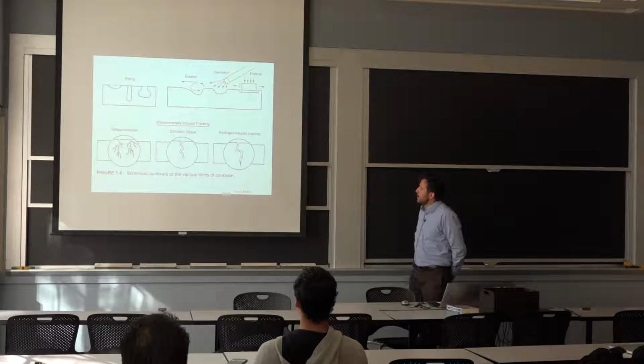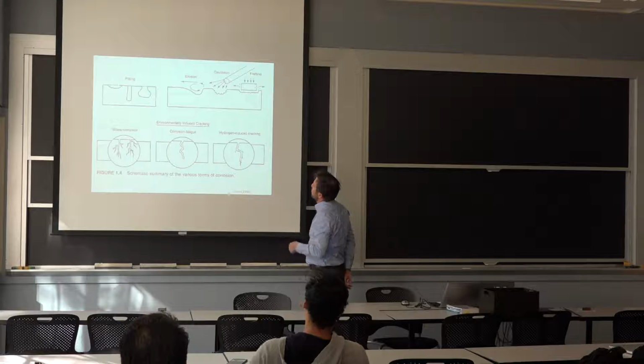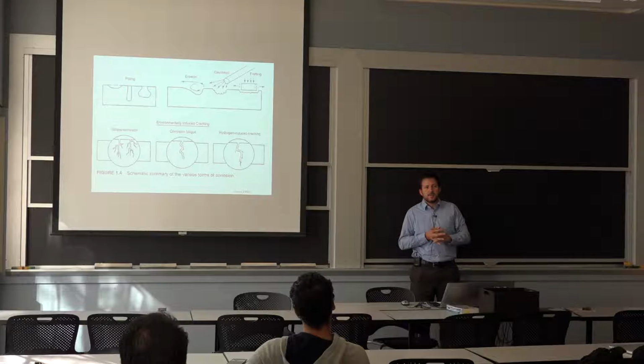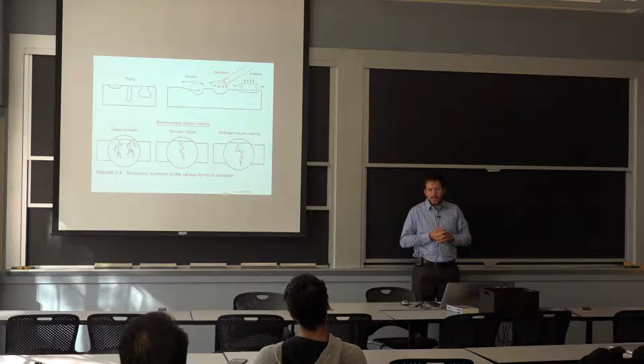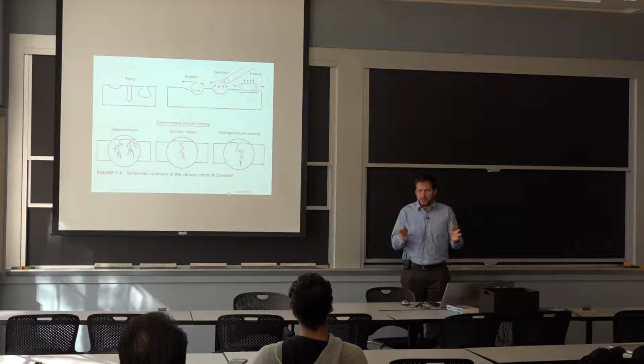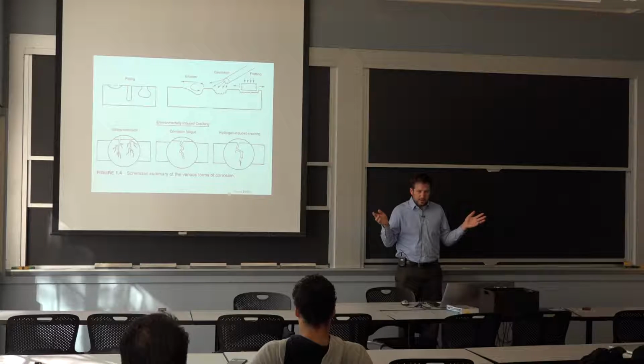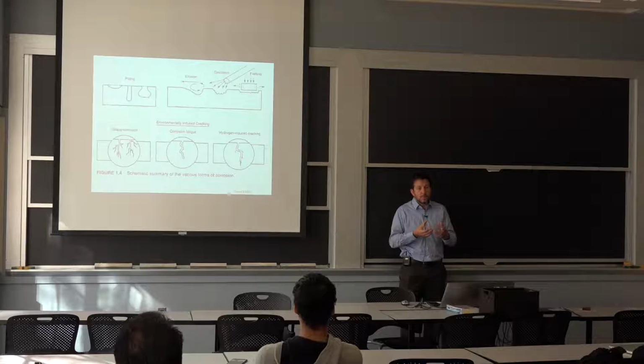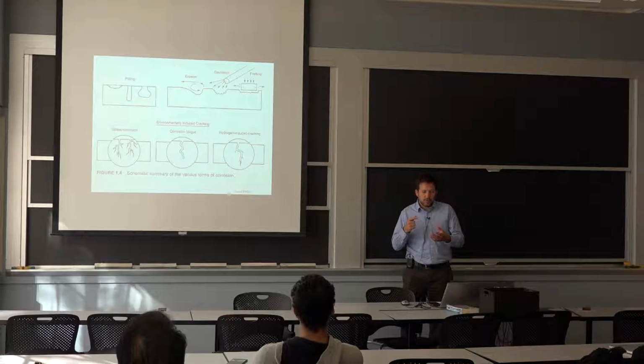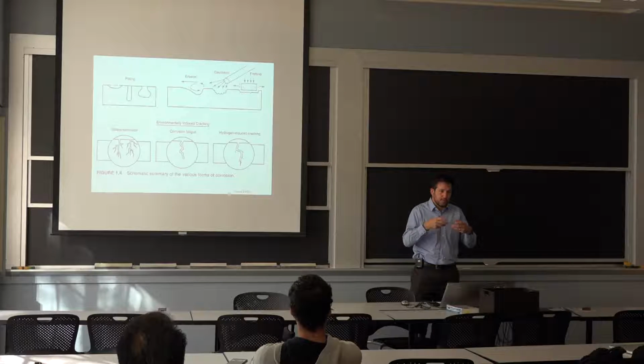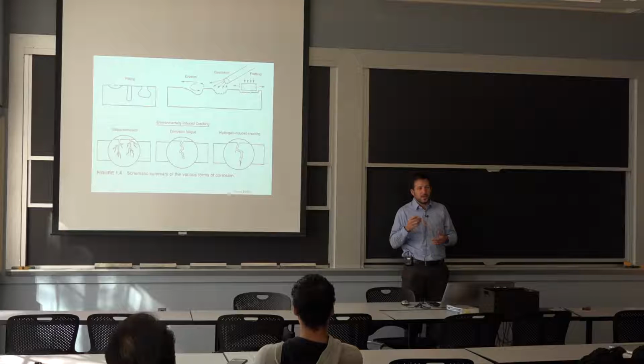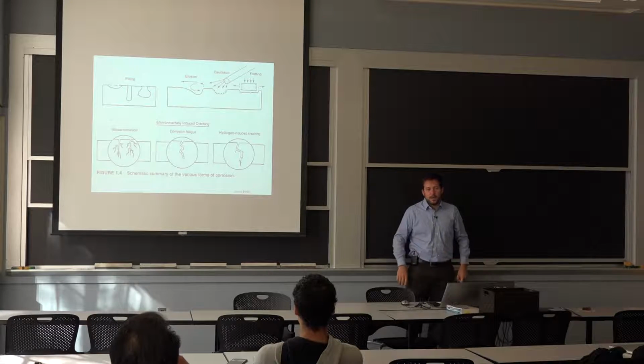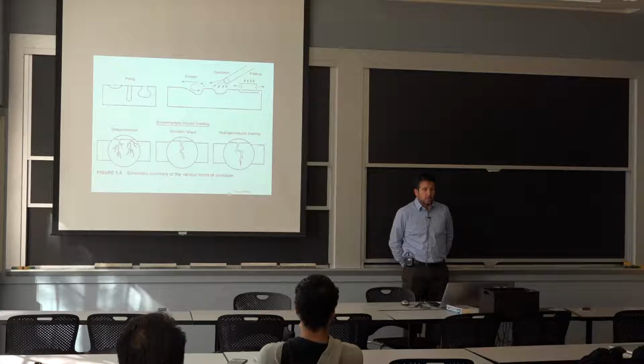This is becoming a little bit more sophisticated with respect to the interaction with erosion. Perhaps one example that I'll give that is very relevant to common day life. If you own a condominium and there's a lot of plumbing in it, and for some reason the plumbers didn't estimate the flow rate correctly into a copper pipe. If there's too much flow into the pipe, you get a situation where essentially you're breaking down the protective film on the inside constantly. So there's enough drag force to prevent the adherence of a protective film, and therefore you keep corroding at a very high rate. It doesn't really happen with public water, but with well water, it can be a problem.